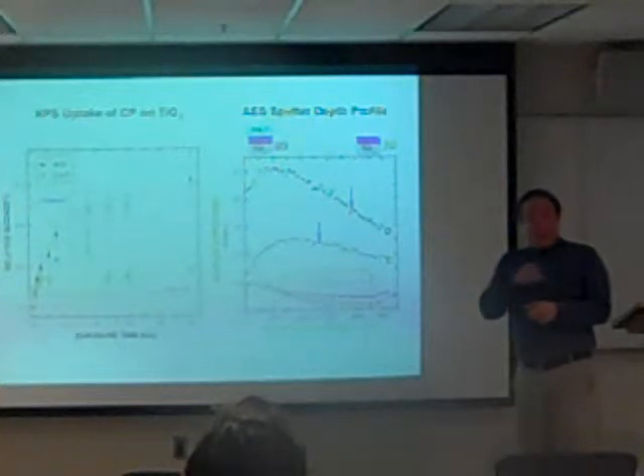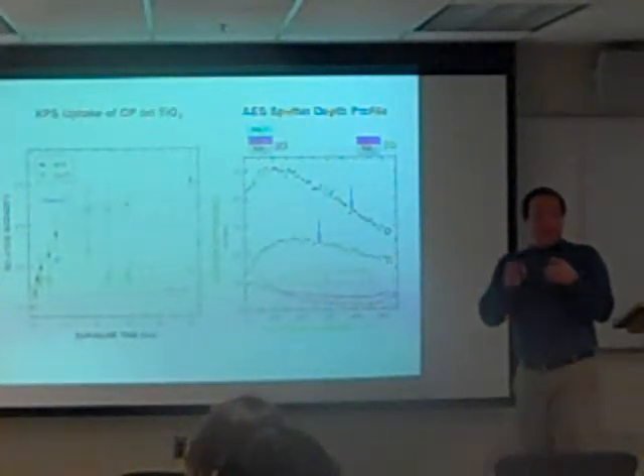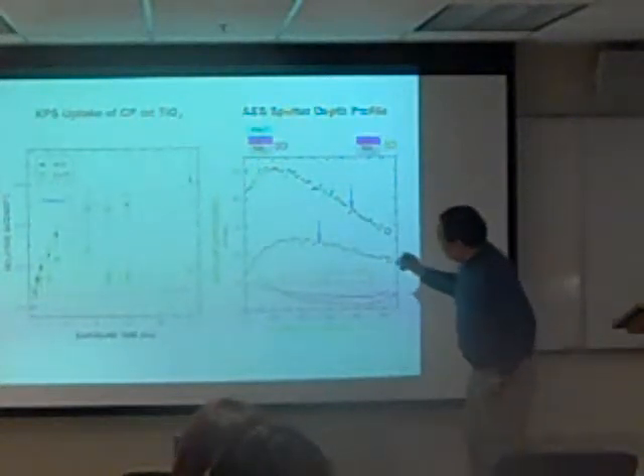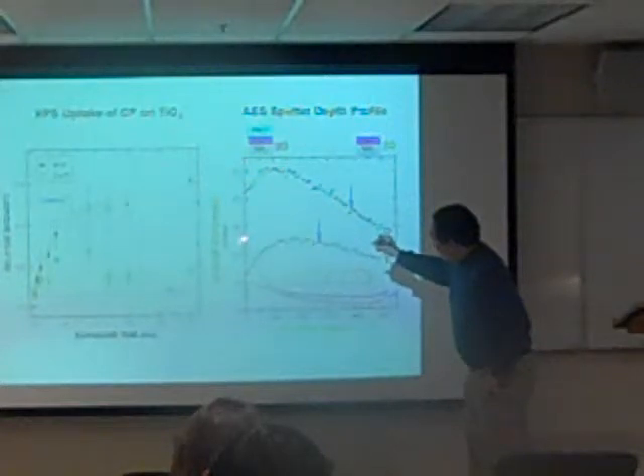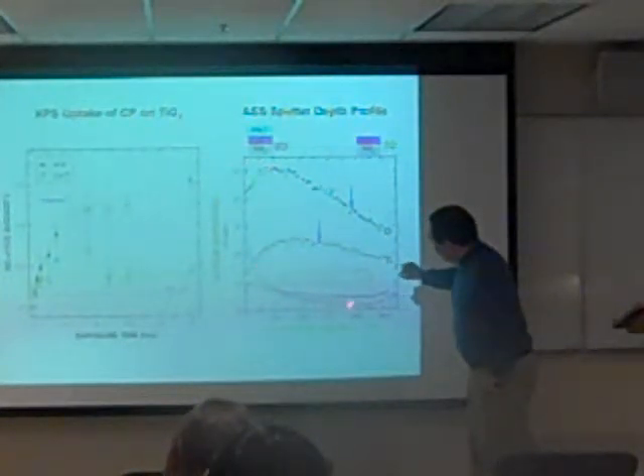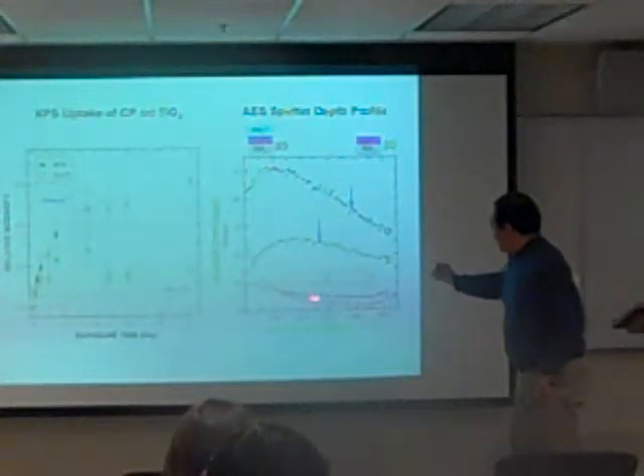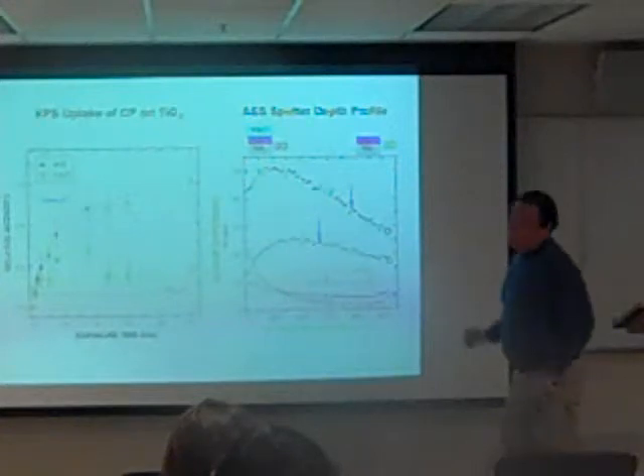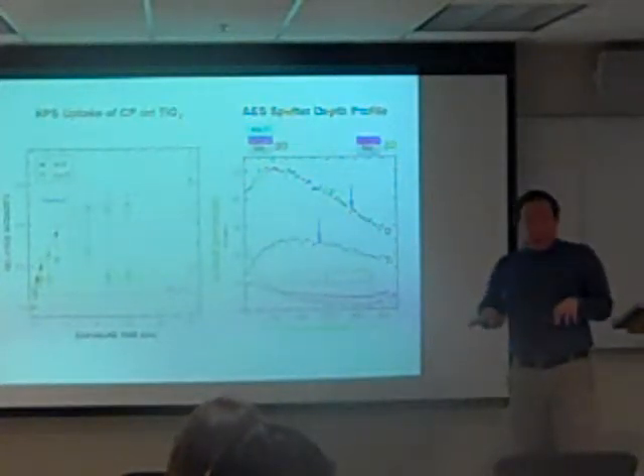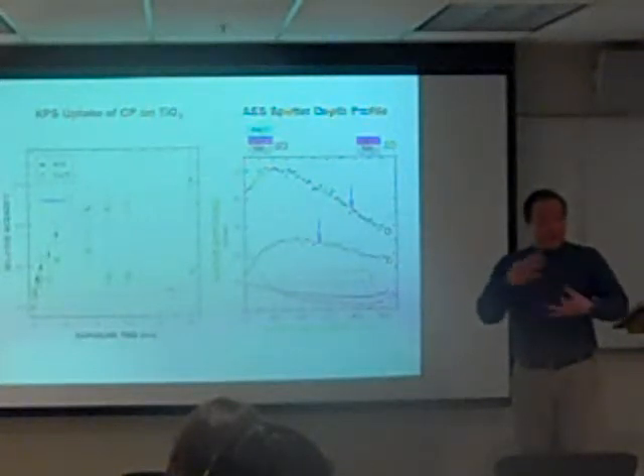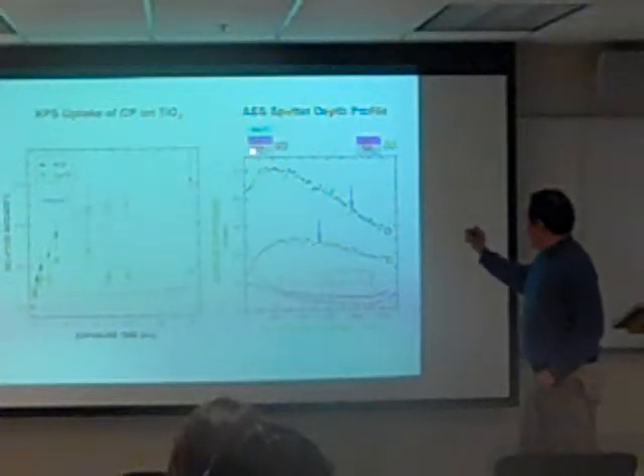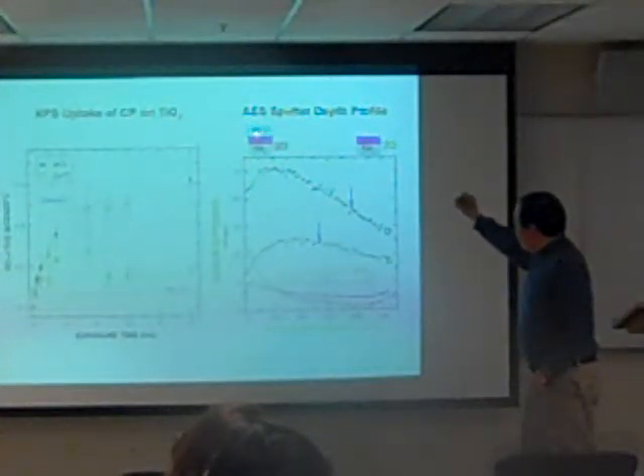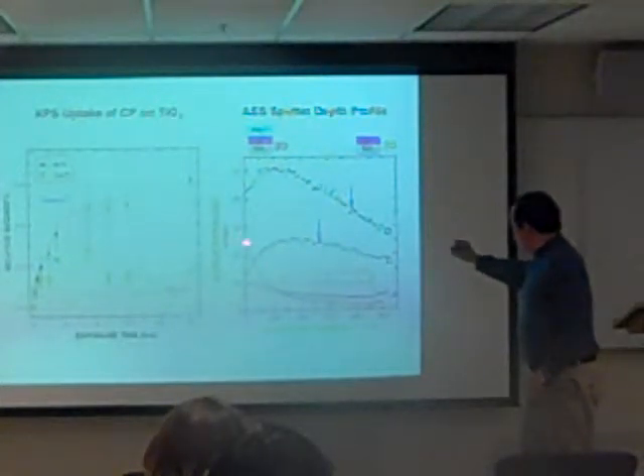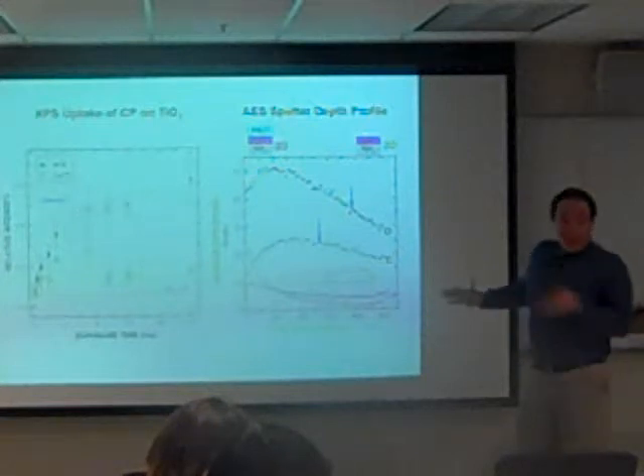This is when we are etching away the topmost layers and simultaneously doing electron spectroscopy. What we see here is that the phosphorus signal is greatest here, and as we etch away the surface, we can see that this drops down, like so. And then at the same time, you see the emergence of a calcium signal here. So the overall picture is that the initial layer as the material grows is calcium rich, and then the phosphate groups grow on top of that, and so we have evidence for, let's say, phosphate islands, and hence the cartoon right here. So this is the TiO2 surface, calcium, and then a phosphate island, and we're etching away. We're basically blasting off the phosphate here, so that's why the phosphorus drops down here. And this is the structure after we etch away that much material.